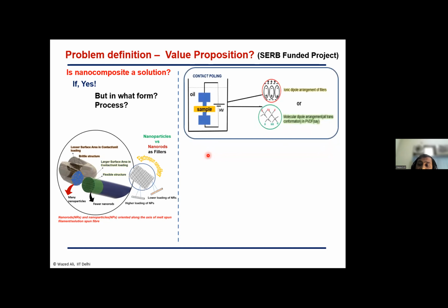But if we talk about electrospinning, that is a unique technique. I just wanted to talk about this process because electrospinning is nothing but the application of high voltage. And with this high voltage, we can use polymeric solution along with filler together, and spin out this nanocomposite fiber, nanostructure rather, where in situ poling can happen, because the polymer as well as the filler is going through high voltage during preparation of the fiber itself, right? So if you get this nanofibrous web, for example, it is already poled in the spinning operation itself, right?